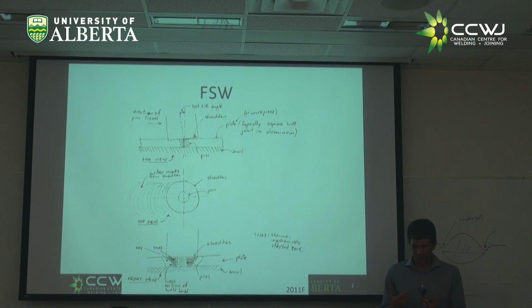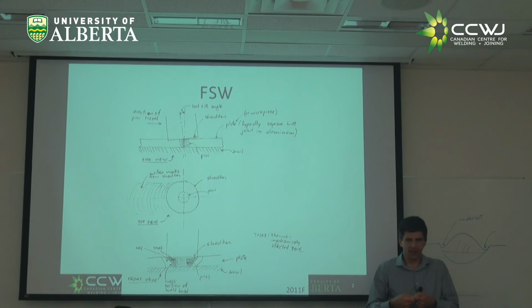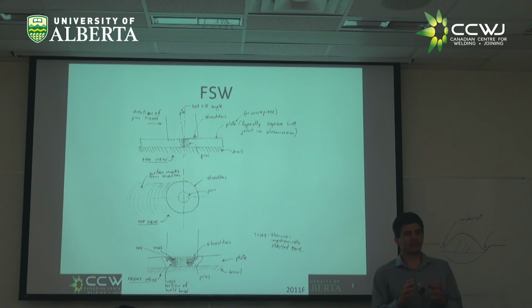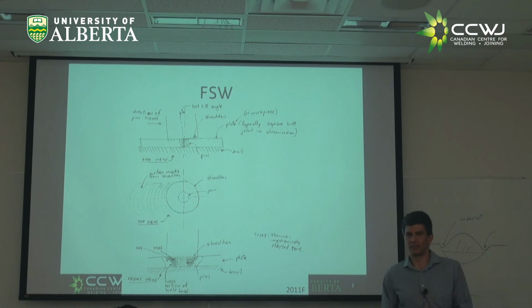So it gets hot. But of course, if you're making force and moving, you're putting in energy, right? Force times distance is work. All that work, where did it go? In heating up that part and bending it, accumulating dislocations until it breaks. So now we have this localized deformation that generates localized heat. And the localized heat makes it locally soft. If it is locally soft, I have localized deformation, and there you go. So in the right conditions, which are not trivial, this thing stirs.